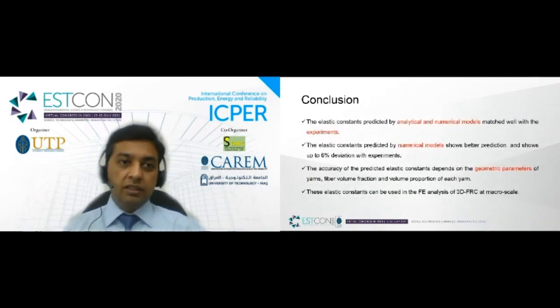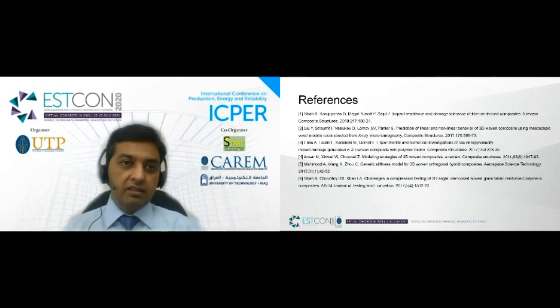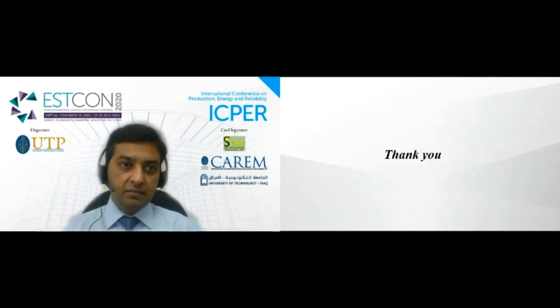Now, conclusion. The elastic constants predicted by the analytical and numerical models matched well with the experiments. The elastic constants predicted by the numerical model show better prediction, with up to 6% deviation from experiments. The accuracy of predicted elastic constants depends on the geometric parameters of yarns, fiber volume fraction, and volume proportions of each yarn. These elastic constants can be used in the finite element analysis of 3D composites at macro scale. These are the selected references. Thank you.